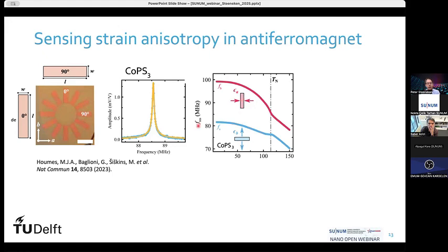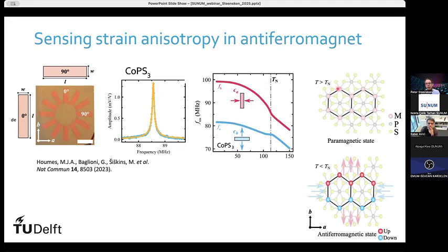And we started looking at this temperature dependence, and this can be understood by looking more at the crystal structure of the material. So here you can see that these metal ions, so these cobalt atoms, they are oriented in hexagons above the Néel temperature. But if you cool it down, you get these antiferromagnetic orders where the magnetic spins are up on this red line and they're down along this blue line. And these magnetic ions, they repel each other. So the membrane starts to expand in one direction and contract in the other direction. So the magnetic ordering causes a variation in the strain in these membranes. And you can imagine that if you have a membrane that is vertical here, the membrane tries to contract, and that leads to a larger frequency increase, like a guitar string, than if the membrane expands, like you see here in this blue line.